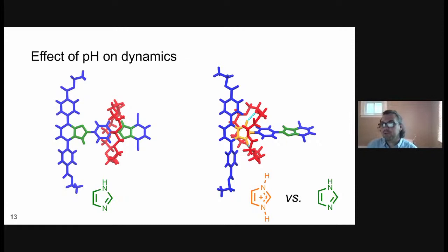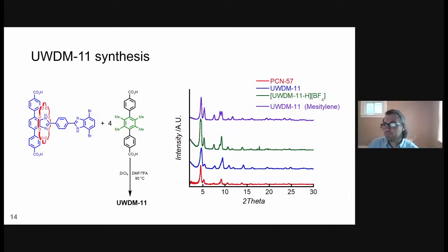And this is something that we would like to translate across into the MOFs. And this is one of the key reasons why we're working with zirconium systems, which are stable enough that we can add acid and they're not going to decompose. So we took this, we hydrolyzed the esters to make the diacid, and we made the MOF, much like the previous examples. And this is now UWDM11.